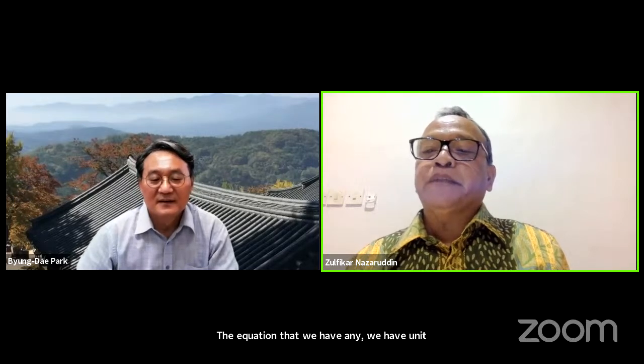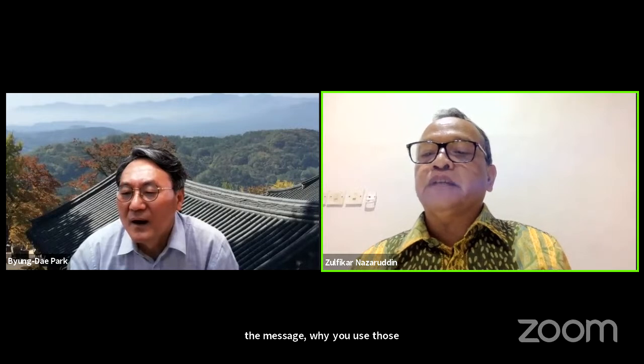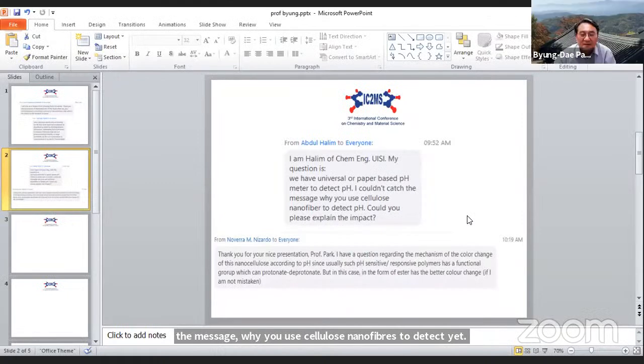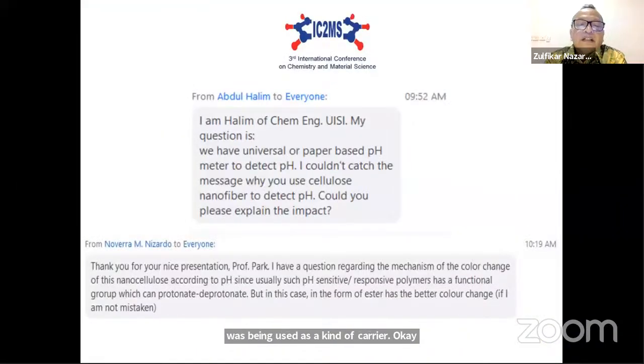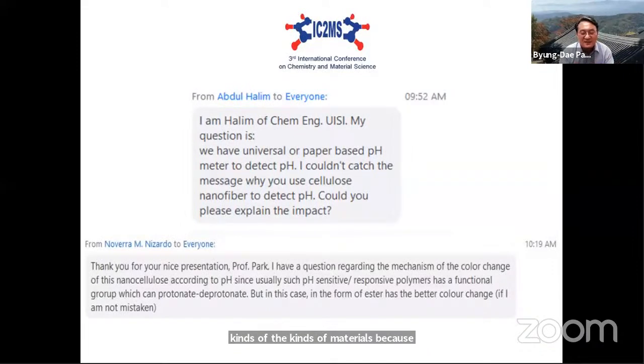The question that we have: universal or paper-based pH meter to detect pH. I couldn't catch the message why you use cellulose nanofiber to detect pH. Could you please explain the impact? Yeah, that's what I said. I answered these questions. What I'm saying is, as I mentioned, the nanocellulose is used as a kind of carrier, not the kind of reactive material, because most pH indicators are water soluble. When you use this pH indicator in any kind of material, when you contact the water, it is dissolved and then it can release, the leaching. That's a problem. So in order to prevent any leaching or solubility in the water, I have to make a very strong bond between the nanocellulose and pH indicator, and then you have no problem for leaching.